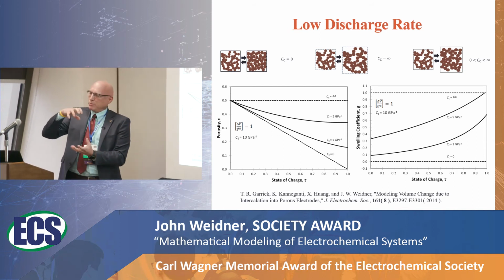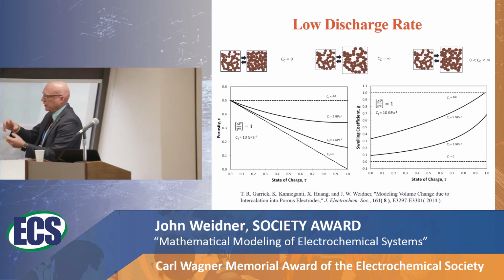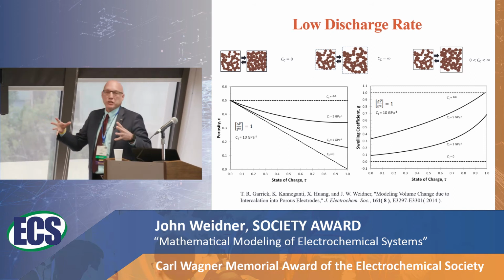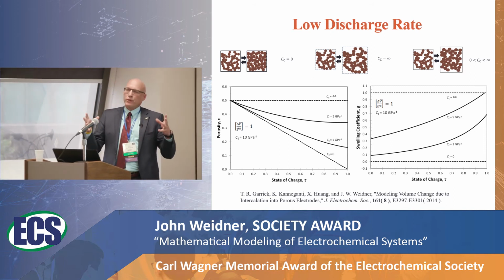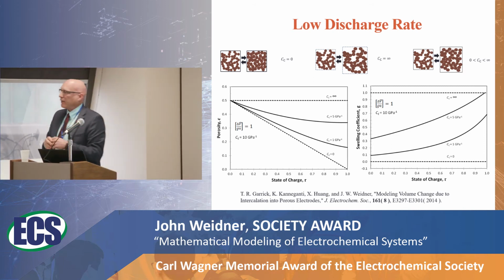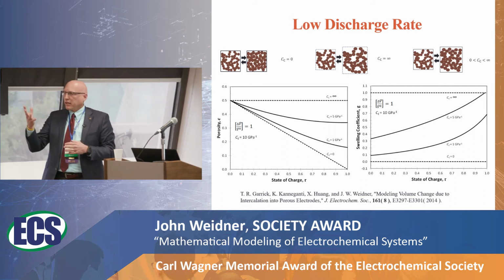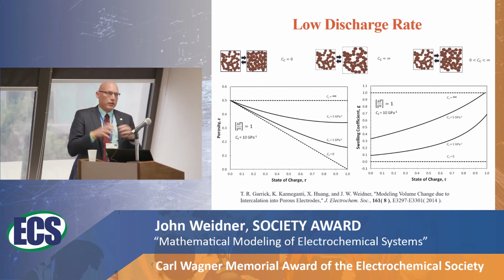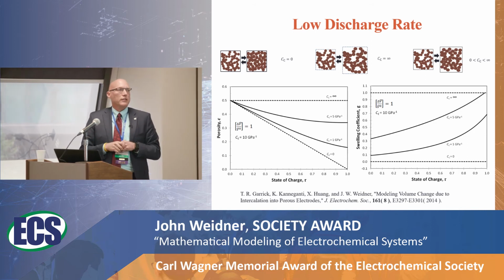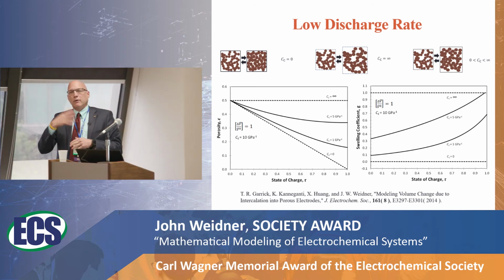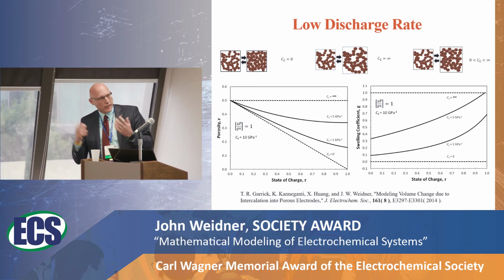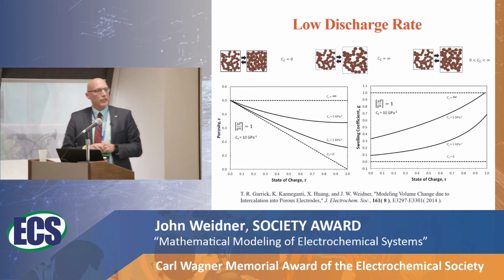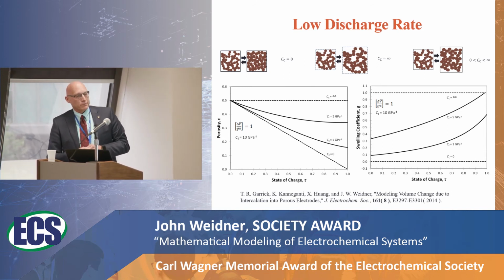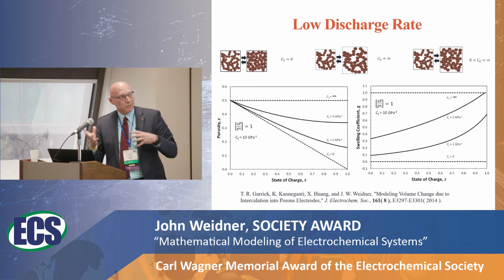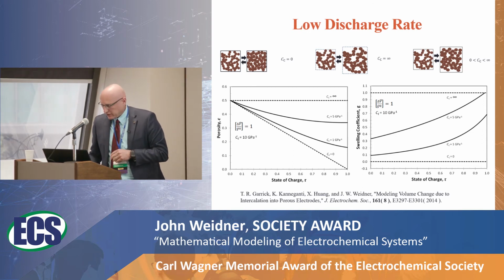So when the can is packed fairly loosely, even if the can is rigid, most of it is going to go into dimensional changes because there's not a lot of resistance, although there's some. And then later on, when the can gets pretty full and it's really pushing against the walls of the can, most of it is going to go into porosity changes. And again, that depends on the relationship between the compressibility of the active material and the can itself.